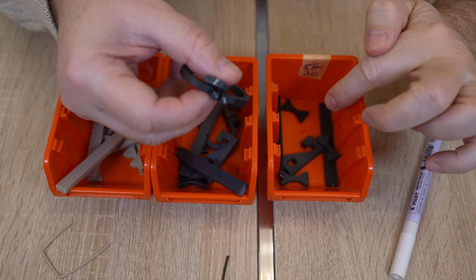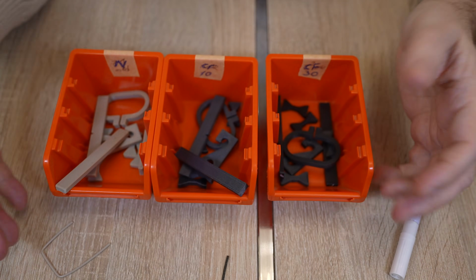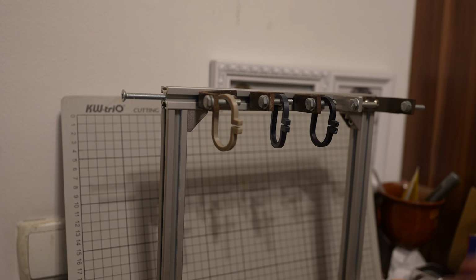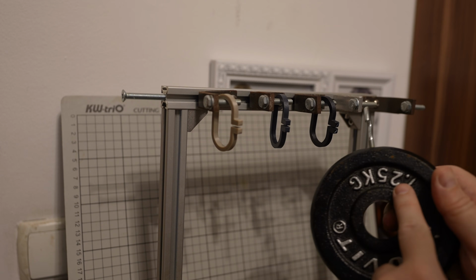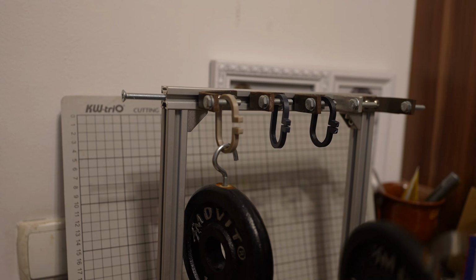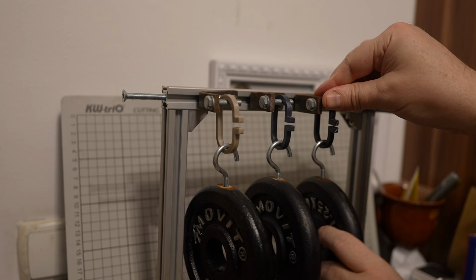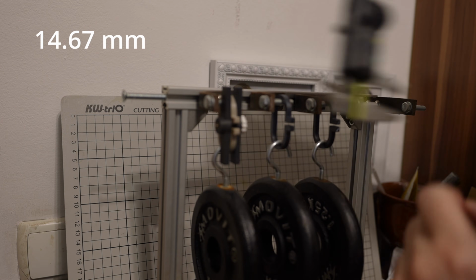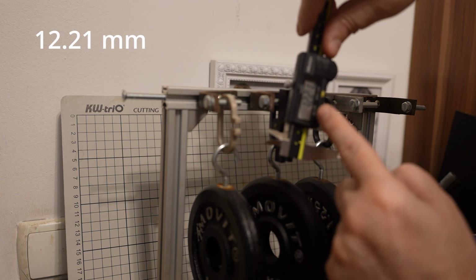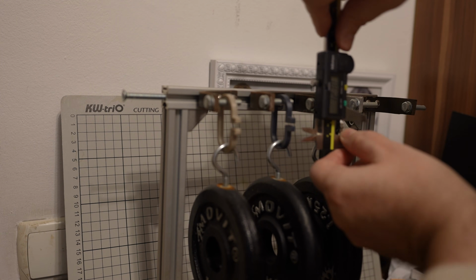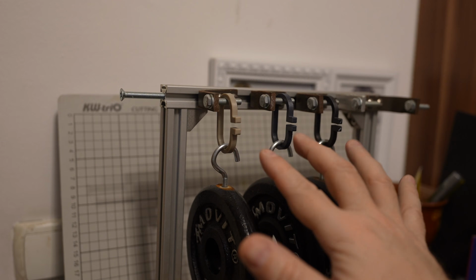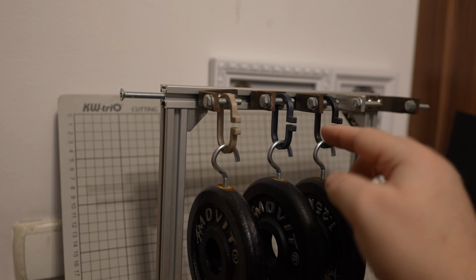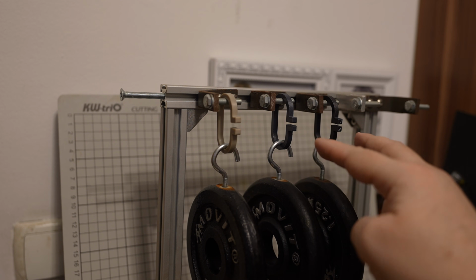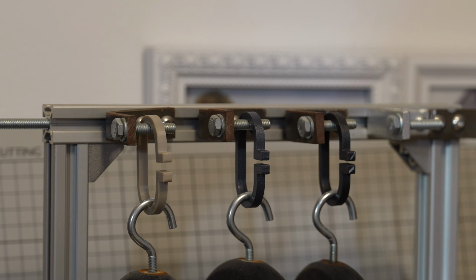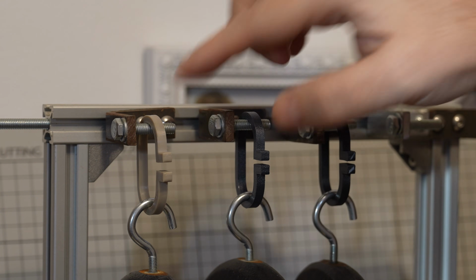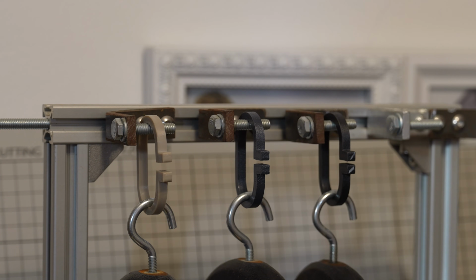Just in case, the CF30 parts I marked with this white line, and they're ready for mechanical testing. Creep test: deformation under a constant load of 1.25 kilograms. 14.67, 12.21, 12.10. From these three, the biggest initial deformation is on the natural material, and the two carbon fibers are really stiff, with very minimal deformation on both of them. This is the last, 5th day, and I already measured them, and only on the natural could I notice some creeping in the first 4 days. Let's remove the rod.